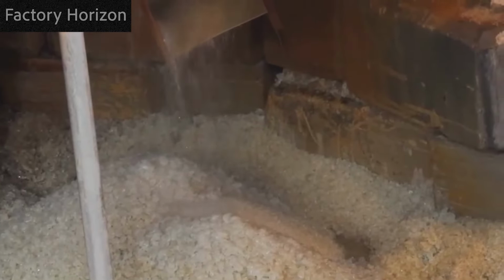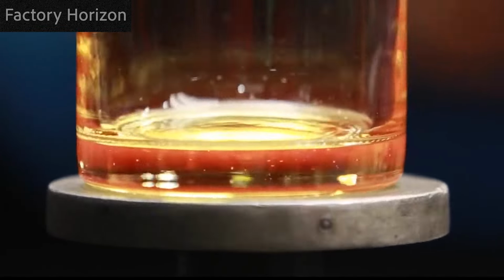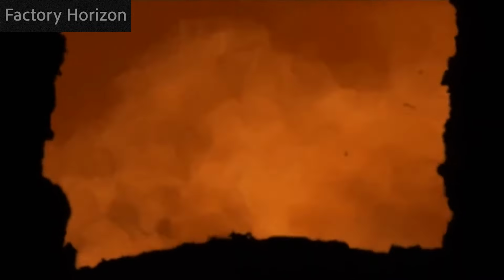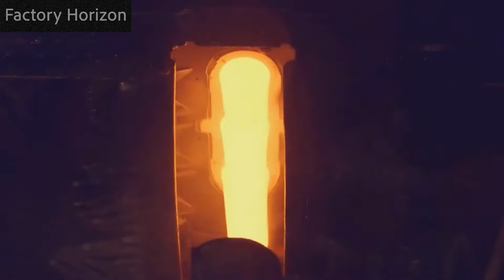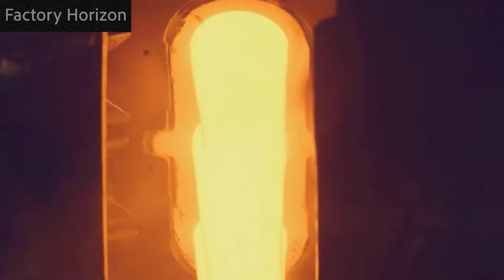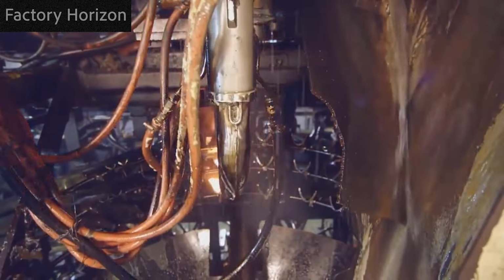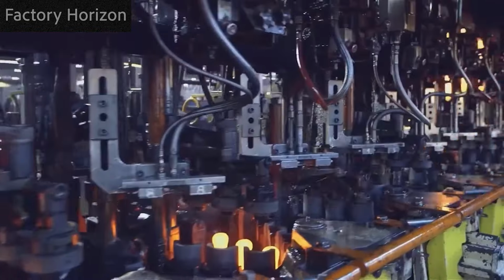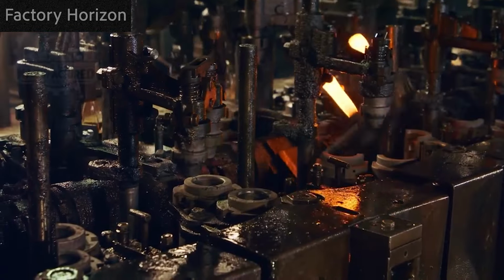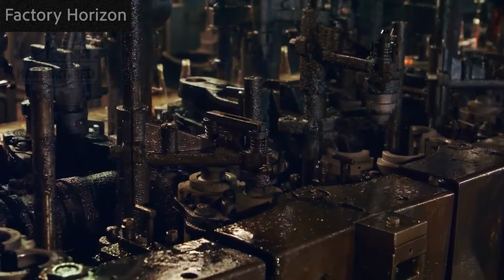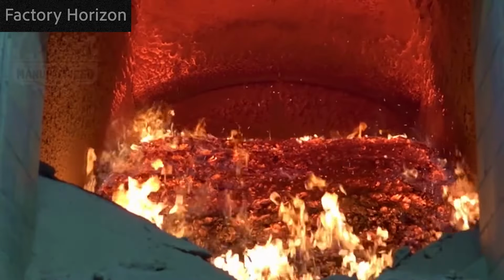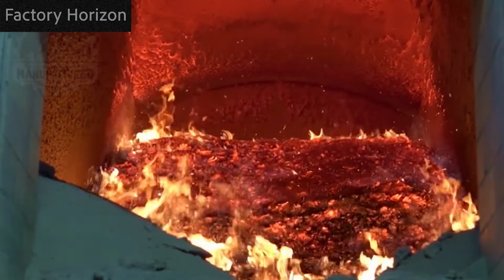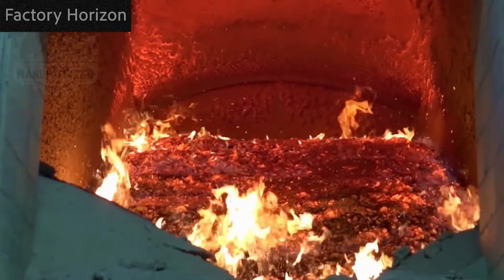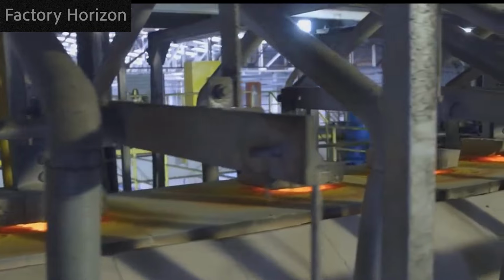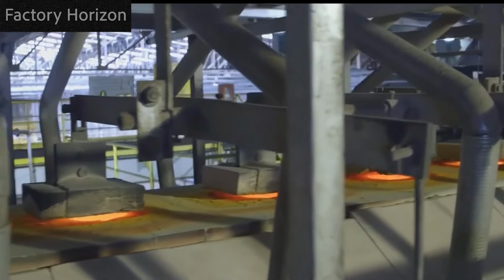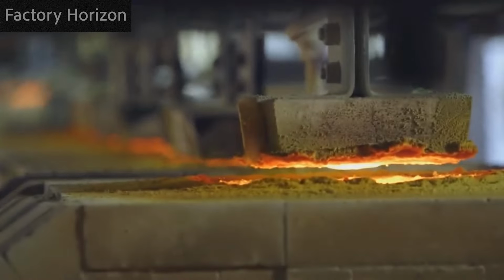Cullet feeds into the furnace through computer-controlled hoppers that maintain precise ratios measured to the pound. Pure recycled glass makes up 70 to 90% of the total batch mix, depending on final product requirements and customer specifications. The remaining 10 to 30% comes from virgin raw materials, including silica sand, soda ash, and limestone. These virgin additions adjust the chemical composition to meet exact industry specifications for strength, clarity, thermal resistance, and color consistency that customers demand.